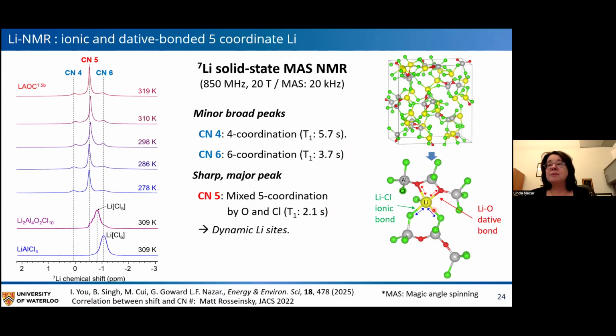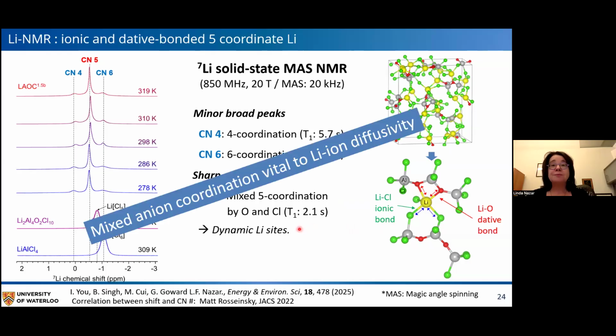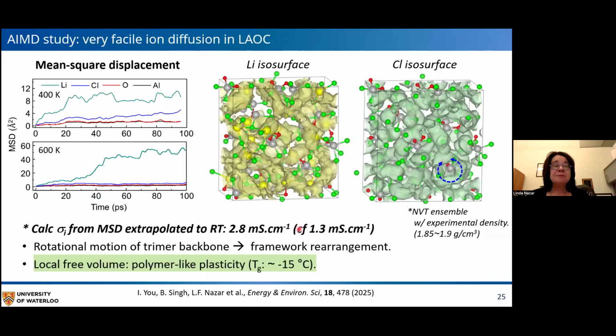And this dynamic nature is, we believe, because the lithium is coordinated in a dative fashion to the oxygen in this aluminum oxychloride chain, and in a somewhat more ionic fashion to the 3 chlorines. So we have a lone pair donation to the lithium from the oxygen and a weak interaction from the halides. And we believe that this is what is underlying the nature of this dynamic response we see in the NMR. And so this mixed anion coordination is vital to the lithium diffusivity.